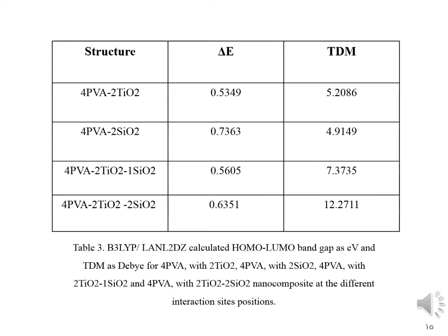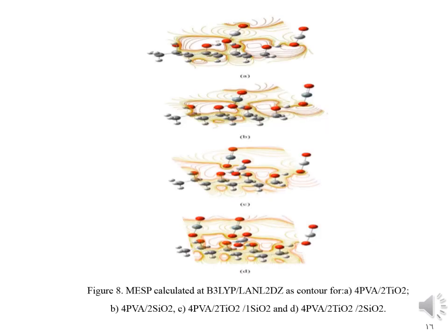For Figure 7c and Figure 7d respectively, Table 3 also presents the effect of adding 1 and 2 units of silicon dioxide on the properties of polyvinyl alcohol to titanium dioxide, where the band gap energy and total dipole moment change to 0.5605 and 0.6351 electron volt and to 7.3735 and 12.2711 Debye for polyvinyl alcohol to titanium dioxide to 1 silicon dioxide, and for polyvinyl alcohol to titanium dioxide to silicon dioxide respectively. Figure 8 presents MESP calculated as contour for the last 4 studied structures. The behavior presented in the figure confirmed that there are fluctuations in the reactivity of the studied structures, where the intensity of the red color increased for polyvinyl alcohol to titanium dioxide and for polyvinyl alcohol to silicon dioxide.